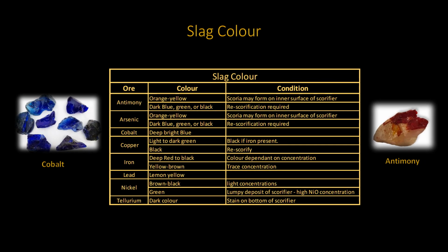The slag color will more often than not be an indication of what may be the base metal in the sample process. Other base metals that may be present may not show up, as they could be obscured. Notice that the copper usually shows up as being anywhere from light green to a darker green. However, if there's a significant concentration of iron mixed in, the copper green color could very well show up as black. A greenish black color may signify a mix of copper and iron.